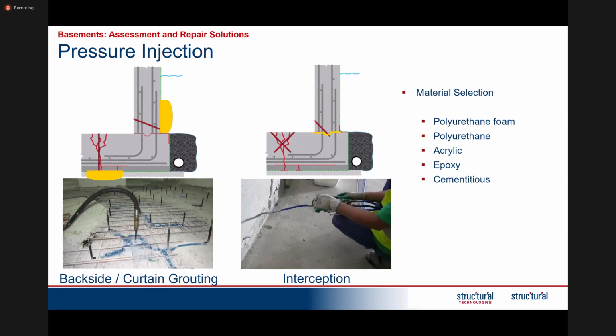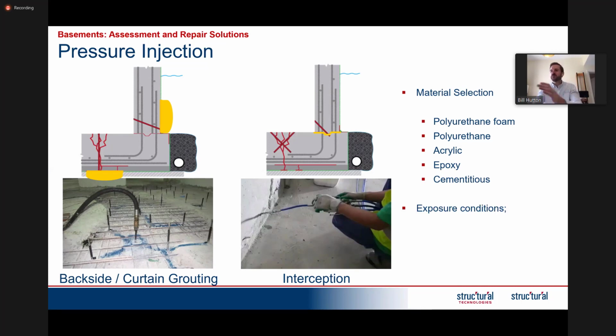Now, there's lots of different materials which can be used for pressure injection. So it's really important to ensure that you select the correct material for your application. So, I've just listed out some typical materials which could be used. It could be a polyurethane foam, polyurethane, acrylic, or epoxy, or cementitious. But really, it's important to select this material based on the exposure conditions. So whether you have a wet or dry exposure, what is the root cause?